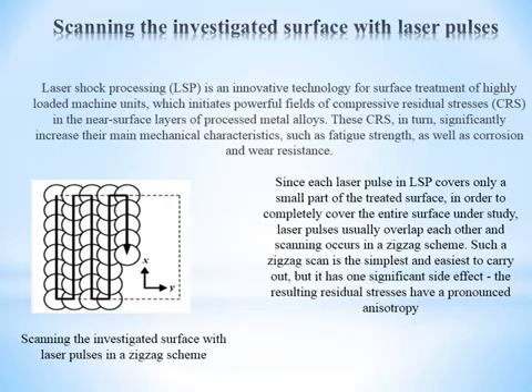In the LSP schemes, a transparent confining layer is used to increase the pressure in the generated plasma. Since each laser pulse in LSP covers only a small part of the treatment surface, in order to completely cover the entire surface under study, laser pulses usually overlap each other and scanning occurs in zigzag schemes.